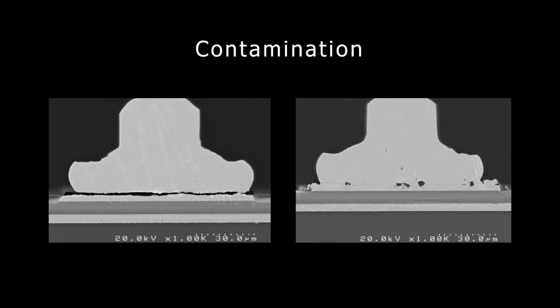These are two examples of failed parts due to contamination. The left bond wire is completely severed. The right is partially separated. Compound semiconductor devices typically use gold bond pads and gold bond wires. If the gold bond pad is contaminated, failures like this will occur.